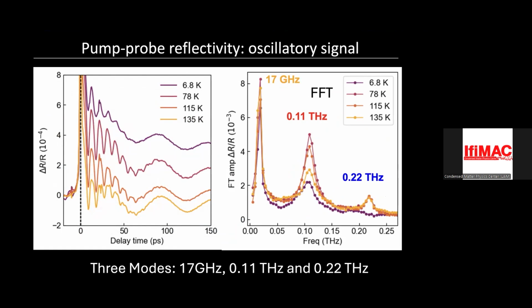And second, just to make sure: I understand that your current understanding is that the matching in frequency of the massive phason and the amplitude mode is serendipity. Yeah, I understand where you're starting from. In fact, it's very peculiar. But the only thing I take comfort in is that if I take all the data that we have, the terahertz data, the fact that there's a radiating mode, the fact that we see current oscillations, the fact that everybody has the same temperature dependence, the fact that X-ray is literally watching the CDW oscillate up and down, there's no other explanation apart from the one I just proposed. I'm open to other explanations, but so far we found none, and it is indeed a real mystery why one is half of the other.